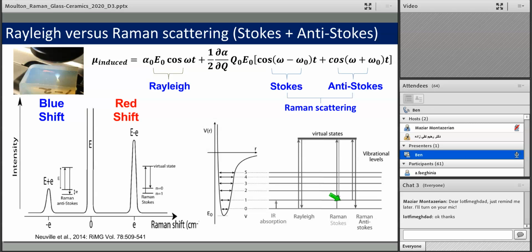And that loss of energy is where the frequency change happens and where the Raman effect takes place. So in the Raman effect, there's sort of two flavors. There can be Stokes scattering or anti-Stokes scattering, where the photon has lost a bit of energy or gained a bit of energy. And in the anti-Stokes case, what we're actually seeing is that the vibrational phonon was excited to begin with, and during this photon-phonon interaction, we decay back to the ground state. So it's gained some extra bit of energy and therefore has been blue shifted to higher energy, producing these modes here.